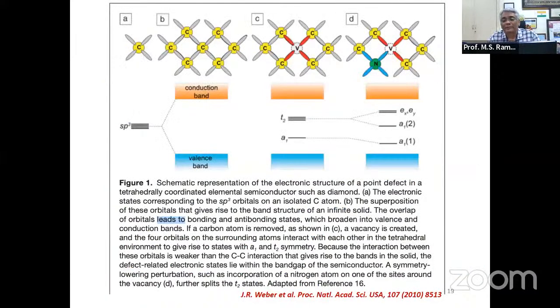So typically when you take a lattice and replace - I'm showing a lattice of diamond here, which is made up of carbon atoms - and replace it with boron, it induces a hole into the system. In a similar way, when I replace carbon with nitrogen, I bring in an additional electron into the system. So I can make a p-type material, p-type diamond when I dope it with boron, and n-type diamond when I dope it with nitrogen.